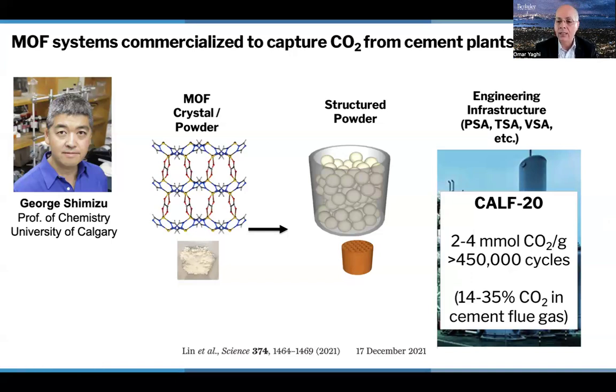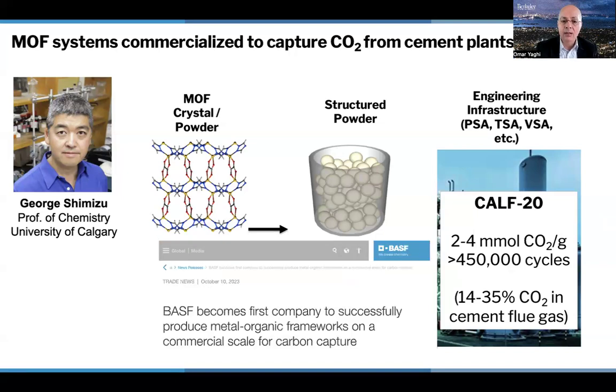450,000 cycles. The key here is that it's great for point sources because it's taking CO2 out of more concentrated, higher concentration streams, as in cement plants. So this MOF is already being scaled up by BASF, as you would be able to see in this media news release, is that BASF is scaling up this MOF to 100-ton quantities to be placed in 3 pilots in Canada, where it's already capturing CO2 from cement plants.